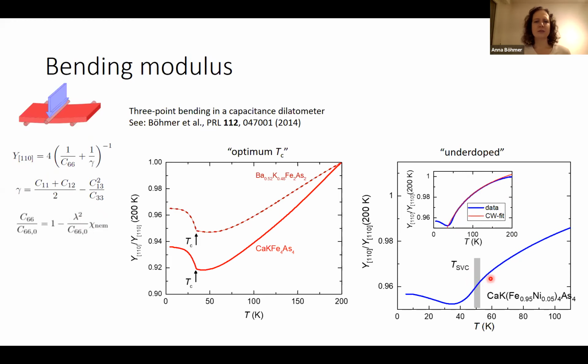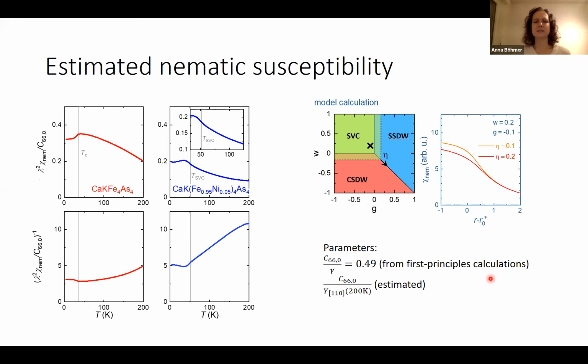So what does it mean for the nematic susceptibility? These are estimates for the nematic susceptibility from these data. There are a few parameters here, but the qualitative temperature dependence doesn't depend significantly on these parameters, so we are very confident about how this looks. The nematic susceptibility in this pure compound increases but saturates, flattens, and then decreases below TC. That looks like a sign of competition, as we are very familiar with already.